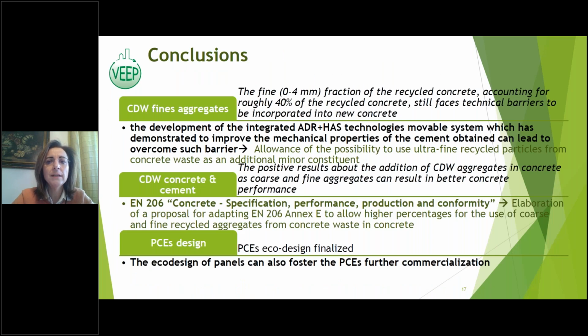Finally, we can conclude that even though there are technical barriers to incorporate the finest fraction of the recycled concrete in novel concrete, the development of the integrated ADR and HAS technologies movable system has demonstrated to improve the mechanical properties of the cement obtained, and this can help to overcome such barrier. Moreover, the positive results about the addition of the CDW aggregates in both coarse and fine aggregates can result in better concrete performance.